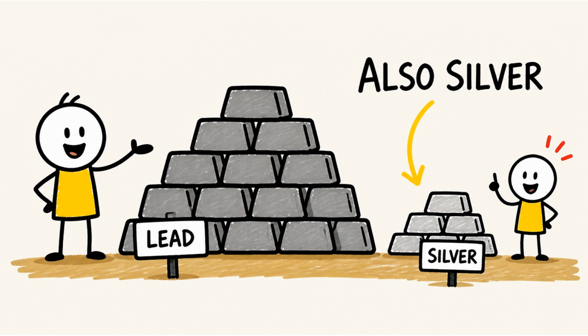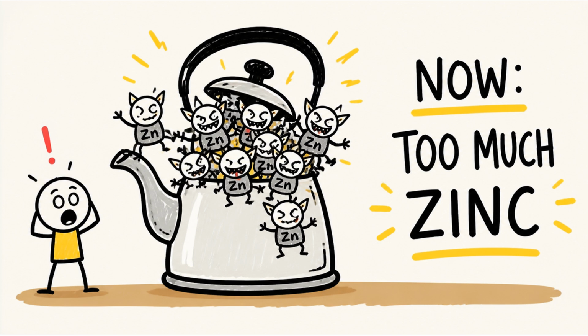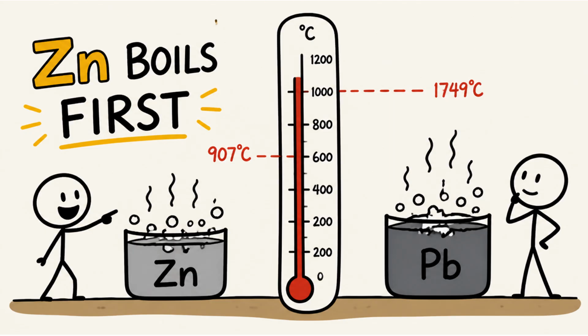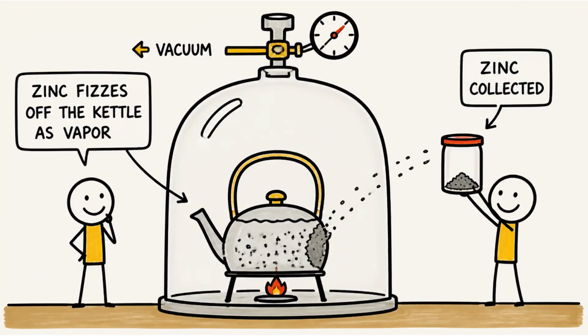But now you've got a new problem. You just poured a bunch of zinc into your lead. So the next step is to take the zinc back out. Zinc, conveniently, boils away at a lower temperature than lead, so they can essentially simmer it off under vacuum and collect it. There's a nice little irony there. You add the zinc to catch the silver, and then you have to remove the zinc you added.